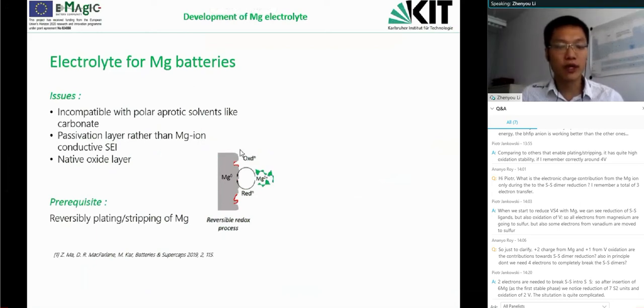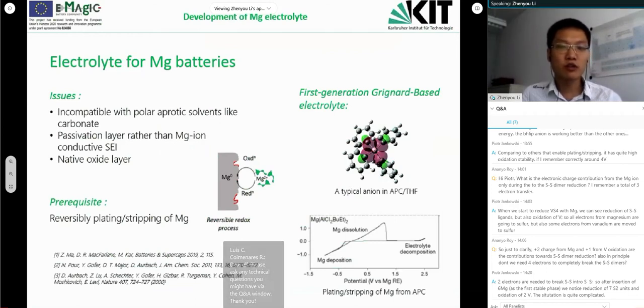In the case of lithium, we always have an ion conductive layer on the lithium surface that protects the lithium anode, so that we can have continuous cycling. But in the case of magnesium, the reaction between magnesium and the solvent results in a passivation layer that blocks further ion mobility. Also, there is a native oxide layer on the magnesium surface, so we need some kind of activation so that we have fresh magnesium towards the electrolyte. Our goal is to achieve reversible plating and stripping of magnesium.